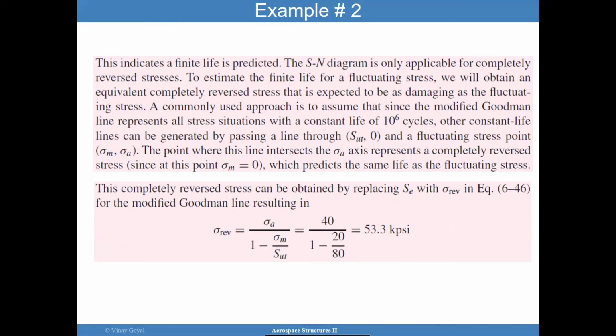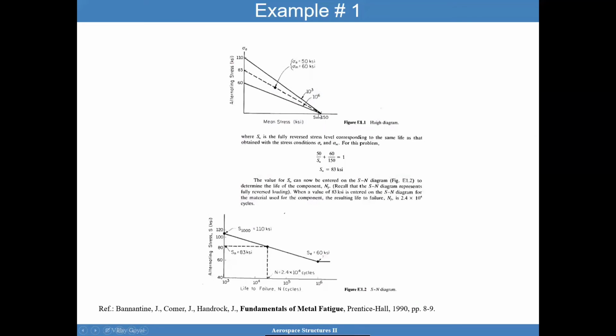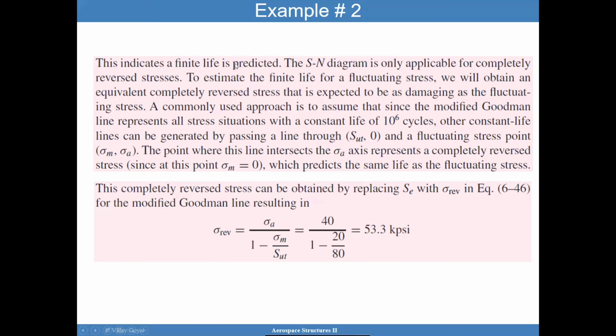So the SN diagram is only applicable for completely reverse cycles, is the problem. So to estimate the finite life for fluctuating stresses, we will have to obtain an equivalent completely reverse stress that is expected to be damaging as a fluctuating stress. So a commonly used approach is to use the modified Goodman diagram, so that it represents all stress situations. And so again, you will generate a line that passes through this point like we did before and this point. And then you find the alternating stress based on that. You extrapolate. The point where this line intersects this alternating stress represents the completely reverse cycle, the equivalent value.